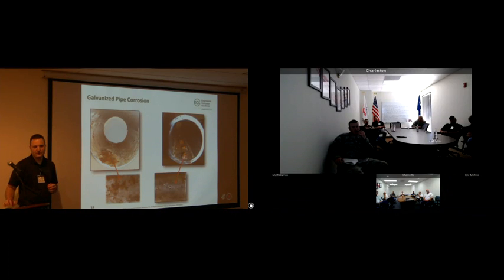The amount of nitrogen you would need would contain so much oxygen, even at 98% purity, that you would cause yourself corrosion issues. That's why it's important when we start talking about it, we're going to talk about not continuously venting. We're going to talk about getting to 98% nitrogen in the pipe network within 14 days or quicker. We want the oxygen out as quick as we possibly can.